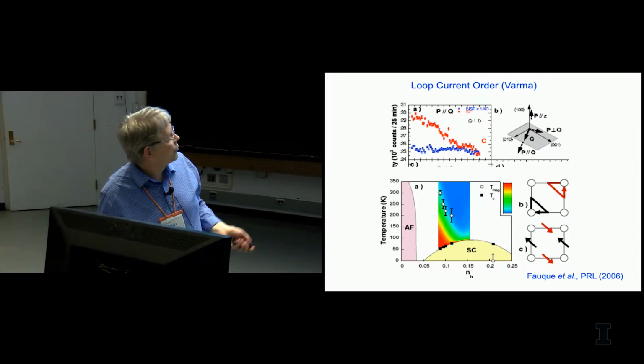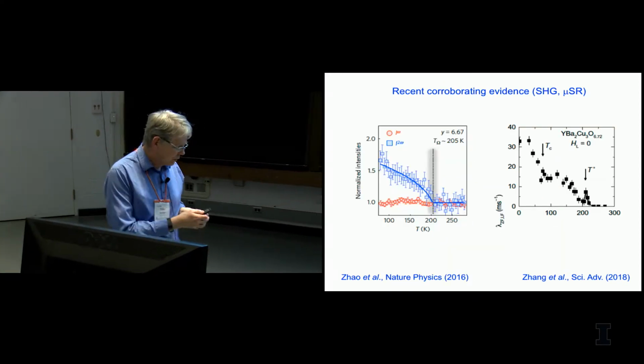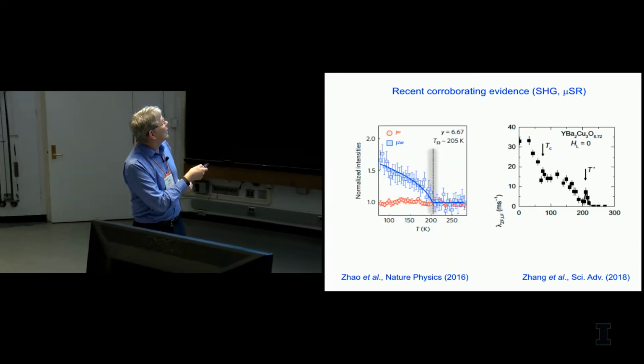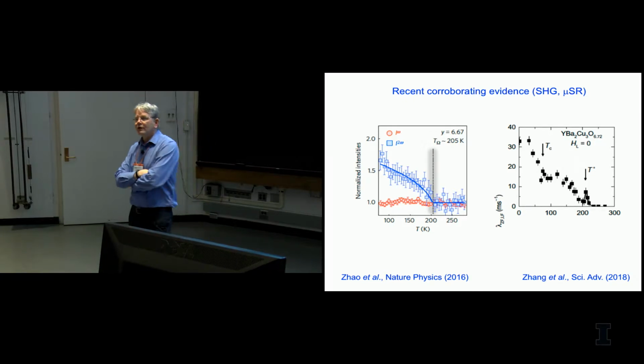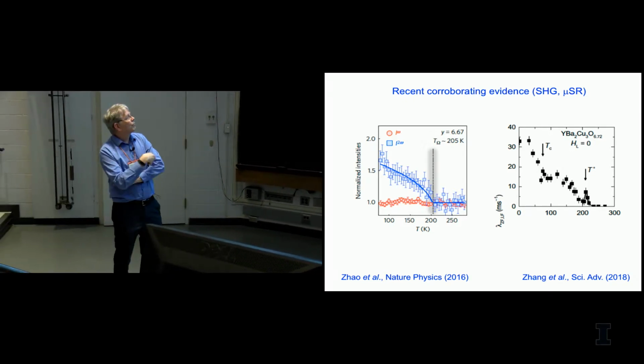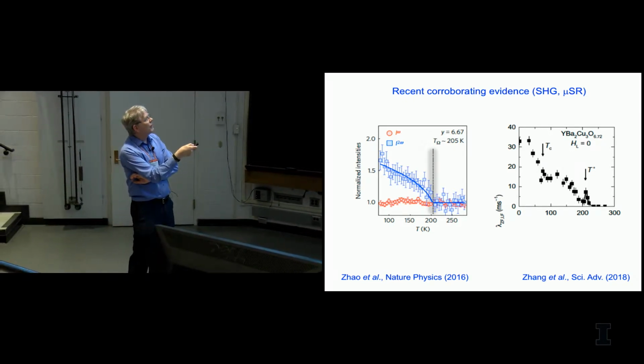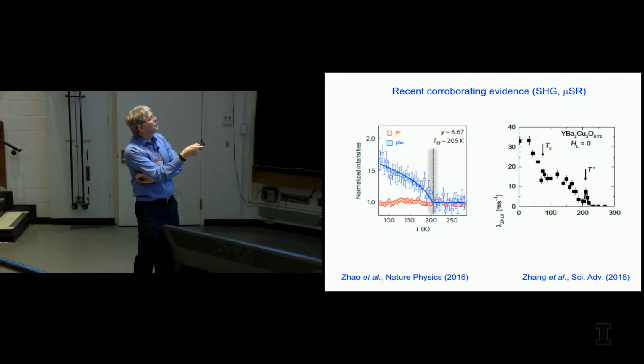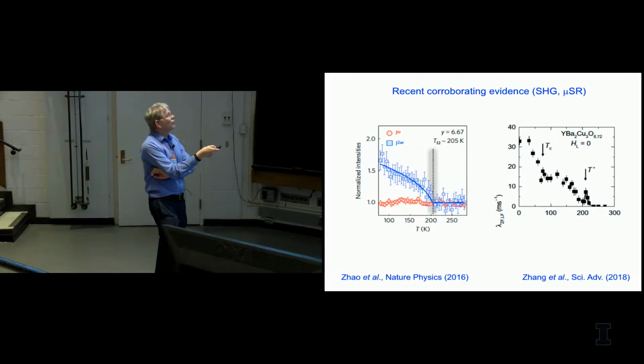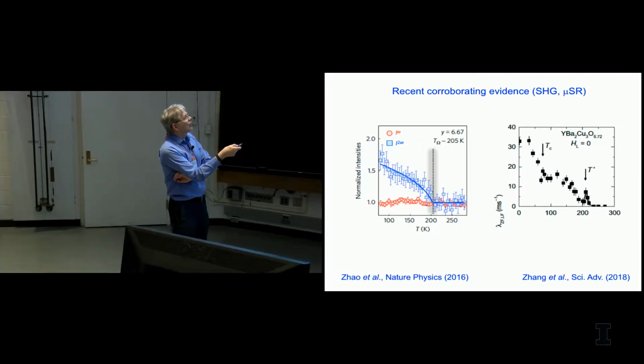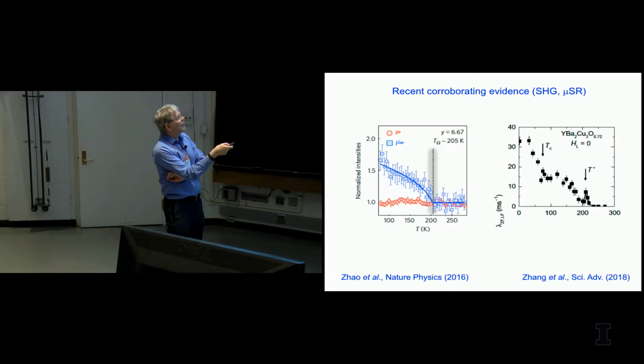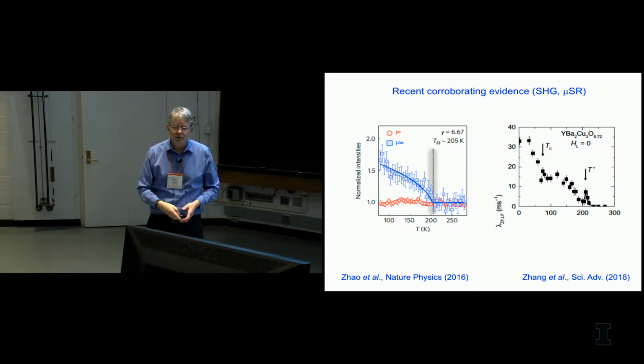And even though you say, well, this was a long time ago, there's been some recent confirmation. Second harmonic generation, which can either detect time reversal or inversion breaking, cuts on at roughly the same temperature. And then there's been a recent experiment from muon, a mu-SR experiment. For a long time, muons were not seeing anything. But this latest muon experiment basically said they have an indication of internal magnetic fields setting on near a temperature of T star.